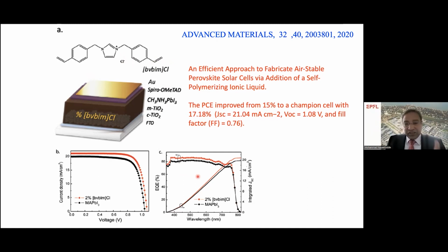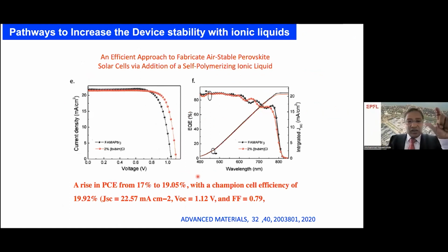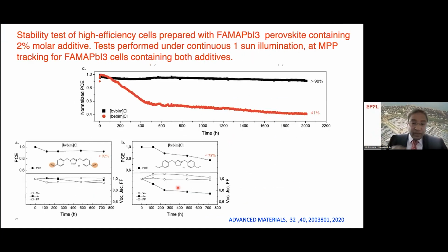If we change this perovskite composition to formamidinium and methylammonium double cation perovskite, the efficiency increased from 17%, that's our reference sample, to 19%. But let me remind you, the data is obtained when you make the solar cells outside the glovebox conditions. Now, if you look at the stability data, it is shown here.